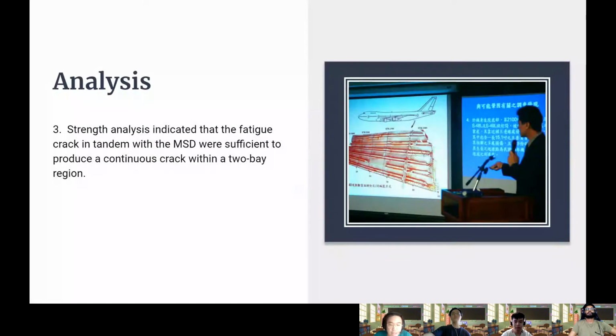Residual strength analysis indicated that the main fatigue crack in combination with the MSD were of sufficient magnitude and distribution to facilitate the local linking of the fatigue cracks so as to produce a continuous crack within a 2-bay region of about 40 inches. Analysis further indicated that during the application of normal operation loads, the residual strength of the fuselage would be compromised with a continuous crack of 58 inches or longer.